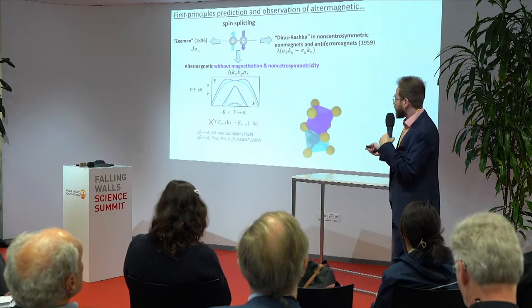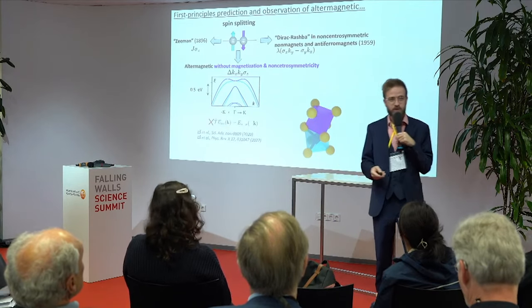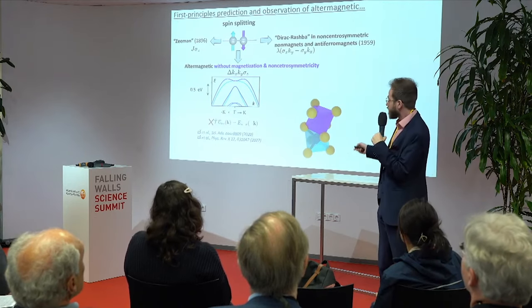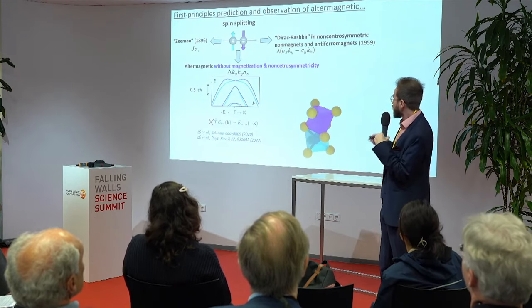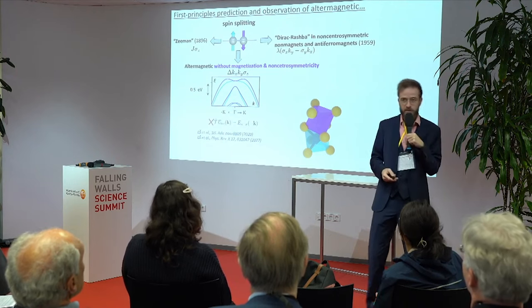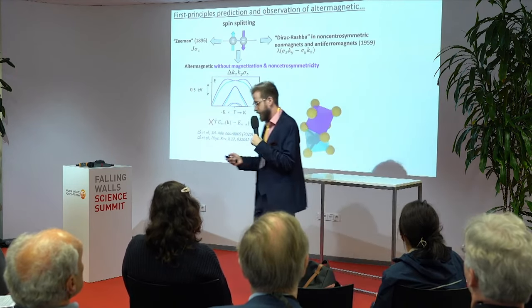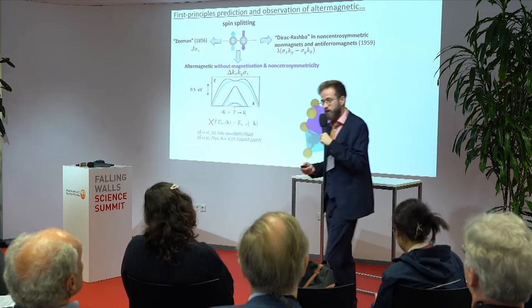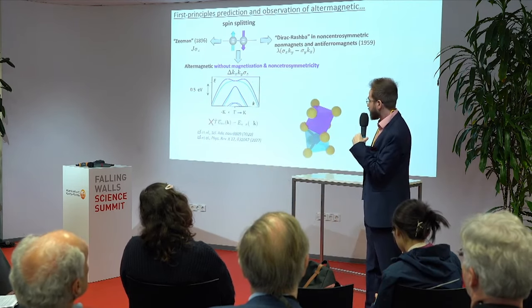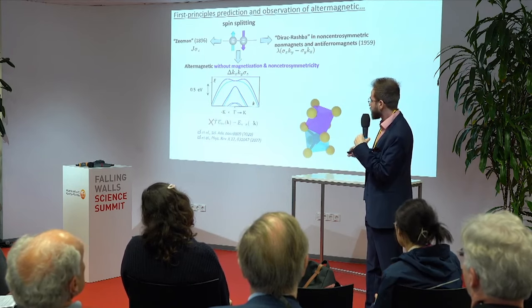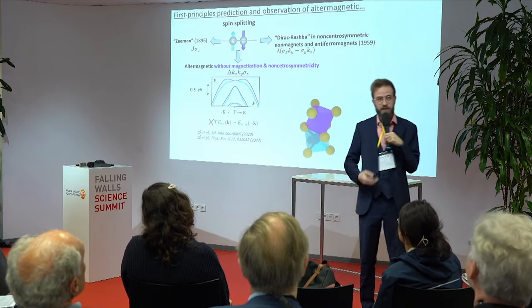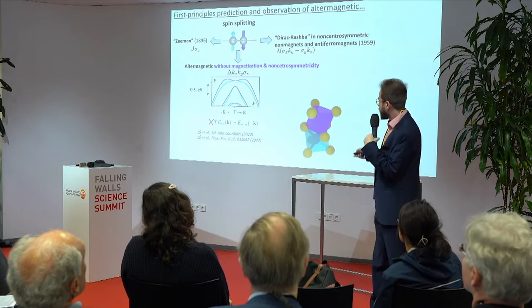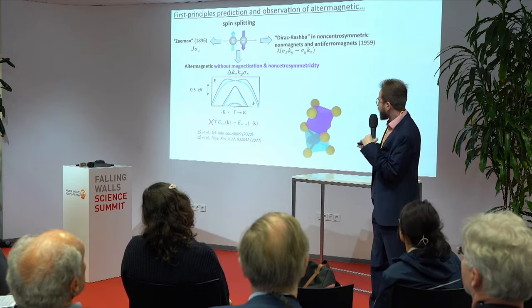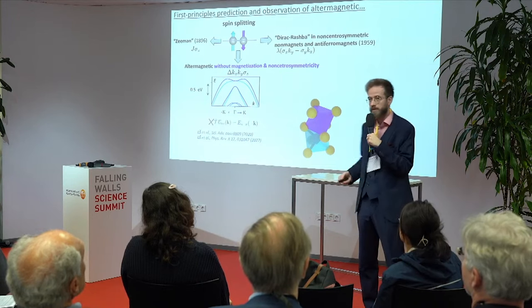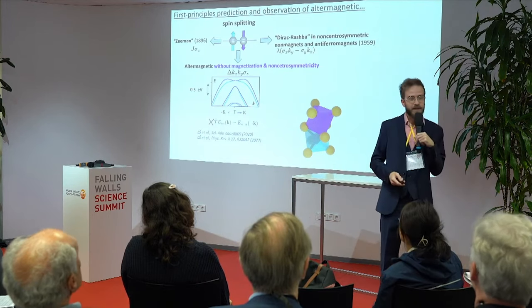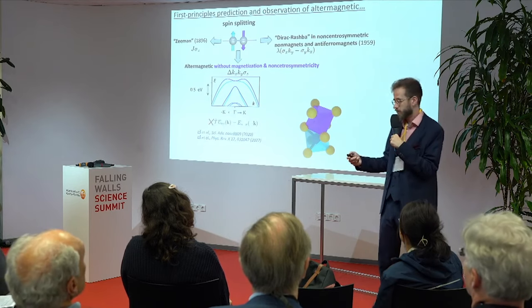Now, the two ways we know from textbooks to split them are either by a ferromagnetic field or by relativistic effects in non-centrosymmetric heavy materials. When we look into the electronic structure of altermagnets, it turns out that we can split the spin states by a third type. This third type is characterized by not requiring any magnetization, and also no non-centrosymmetricity or relativistic effects. And this has important consequences because the splitting can be super strong.